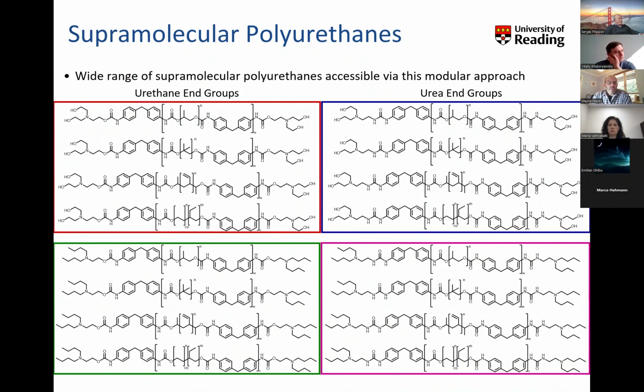So once you've made your pre-polymer, you really can vary the structure of your materials quite dramatically and control those structures such that you can change the polymer by only a couple of atoms. Shown on the left-hand column are the urethane series that we've developed with a range of different polymer mid-blocks: polypropylene glycol, polyisobutylene, and the polybutadiene derivatives shown below, with either alcohol end groups or alkyl end groups.